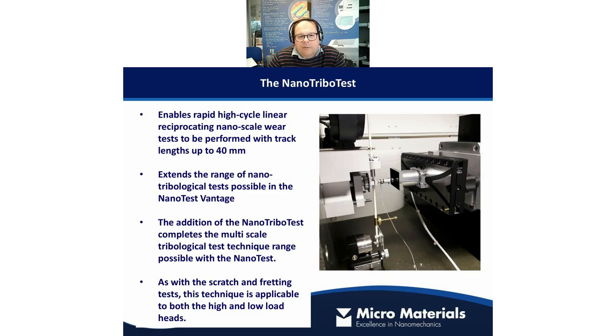We are able to combine that with additional techniques. So we could even do this in a fluid. We could do this with, for example, the sample being an electrical connector, and we could pass electrical charge between the probe and the sample and look at how the electrical contact resistance changes as the test progresses.